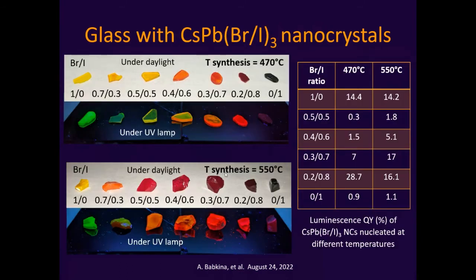But you know, pure halogen perovskite nanocrystals are not very interesting, because everybody is making them. So we decided to make mixed halogen perovskite nanocrystals. Firstly, we took bromide and iodine ions, because we have synthesized bromide perovskites and iodide perovskites. Why not mix them? We made a glass roll at different temperatures. We also heat treated them.